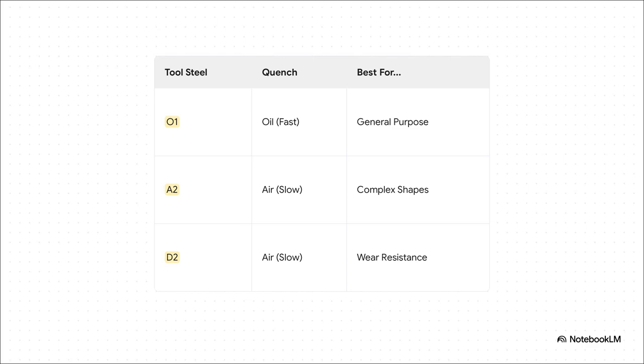And matching the steel to the job is key. For example, a basic general-purpose tool steel like O1. It needs that fast oil quench. But what if you're making something really complex, where any warping would be a disaster? Then you'd go for an air-hardening steel like A2. And if you need something to take an absolute beating, like a die that needs extreme wear resistance, you'd pick a high-alloy air-hardening steel like D2. Different steels, different recipes, different results.